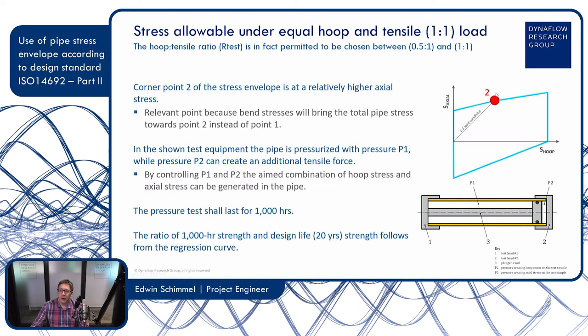And you might think, why do we want this second point? There's a very good reason for it. Because if we just pressurize a pipe, then we have stresses on this line, somewhere around this corner point, depending on how far we load it. But in an actual piping system, we have additional axial stresses due to weight. There's also thermal expansion that creates additional bending stresses. So there are a lot of additional loads besides the pressure load that create additional axial stress, but no additional hoop stress. So in actual applications, the load condition is more in this area. And this 1:1 load condition is a good representative for the actual stresses in your pipe.